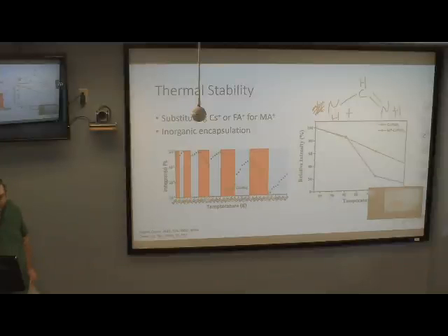So we come across the term Goldschmidt tolerance. You're talking about the stability of a perovskite, so that's something you'd want to mention, because that's essentially what they're testing. With temperature, you're essentially changing the crystal phase and its ability to bounce back and forth. That has to do with those cations that you mentioned. Some are too small, and so that leads to the degradation of phase change.